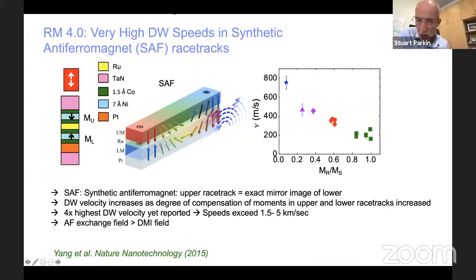And that's what's nice in these synthetic antiferromagnet surfaces: they are still magnetic, but in aggregate, the volume has no net magnetic moment. And then we discovered unexpectedly that when you pass current through these structures, the domain walls would move 5 to 10 times more efficiently than in the respective single racetrack. Or if we change the interlayer coupling ruthenium thickness slightly, so the coupling changed from antiferromagnetic to ferromagnetic, then the speed would be 5 to 10 times lower.